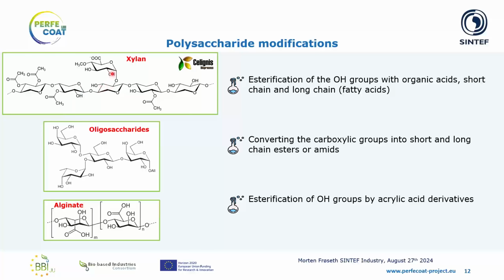We have the OH groups and the carboxylic acid groups in xylan. In the saccharides, we have OH groups. And in alginates, we have acid groups and OH groups. So we will use these as kind of attack points, reactive sites to do functionalization. The OH groups we can esterify by reacting with organic acids. They can be short chained or long chained, depending on the final property that we want. And we can even use the fatty acids that are also produced in the project to get the alkyd look-alike material in the end.